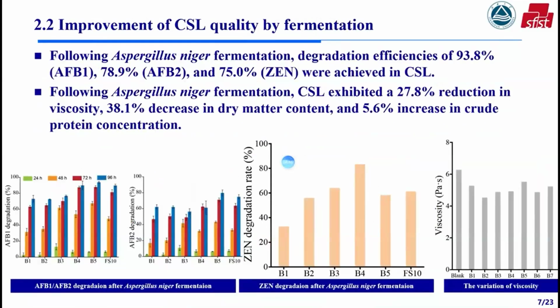To reduce mycotoxin contamination in CSL, we attempted to inoculate food safety strains for fermentation. We verified that the food safety strain Aspergillus niger FS10 can grow in 10% CSL and decrease AFB1, AFB2 and ZEN in CSL. After 96 hours of fermentation, the degradation rates of AFB1, AFB2, and ZEN reached up to 93.8%, 78.9%, and 75% respectively. After fermentation with Aspergillus niger, the viscosity of CSL decreased by 27.8%, dry matter by 38.1%, while crude protein content increased by 5.6%.